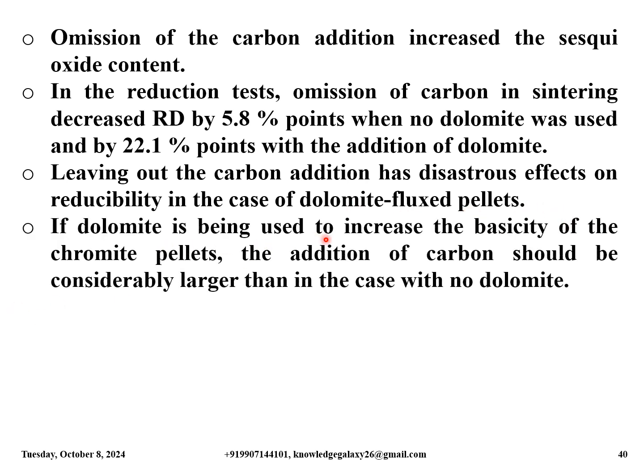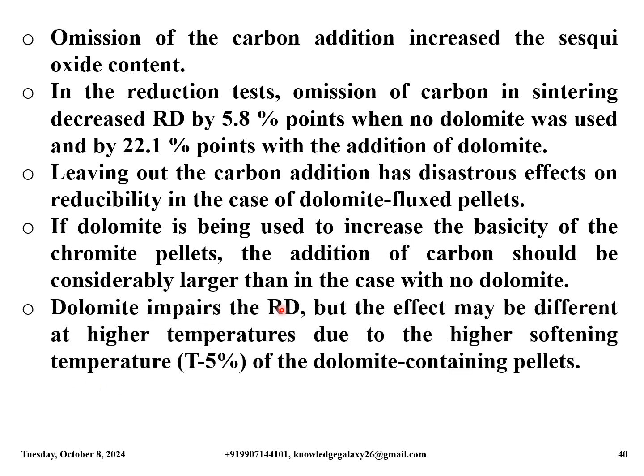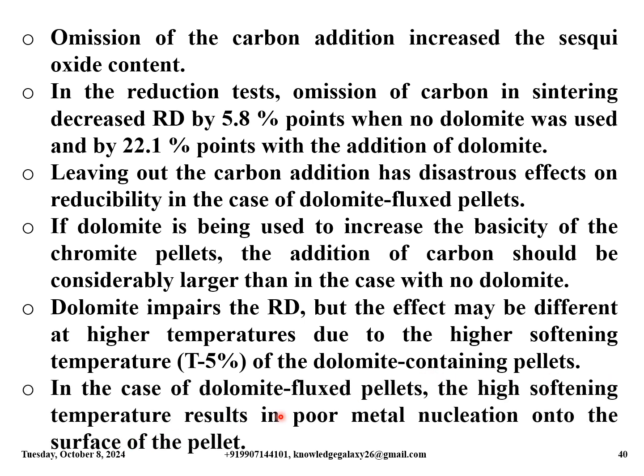If dolomite is being used to increase the basicity of the chromite pellets, the addition of carbon should be considerably larger than in the case with no dolomite. Dolomite impairs the reduction degree, but the effect may be different at higher temperatures due to the higher softening temperature, that is T5% of the dolomite containing pellets. In the case of dolomite fluxed pellets, the high softening temperature results in poor metal nucleation onto the surface of the pellet.